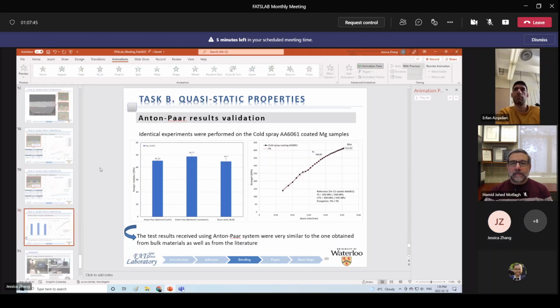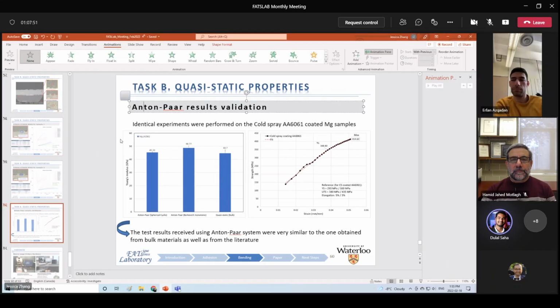There is no other way we can estimate the coating property, because the coating was only maybe 200 microns thick, and there was a lot of porosity and other defects in the coating. It's very brittle, so we cannot actually load it in any other way to estimate the properties of the coating.